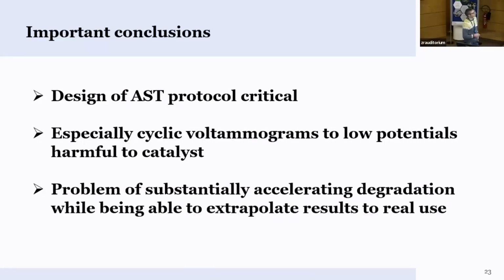So we know that this design is critical, but the design is often a little bit arbitrary, although it's more or less standardized. But it's really important to understand what happens during the different stages of such a protocol. And we know that not only the extension to high potential where you have the oxidation, but also the reduction potentials are quite harmful to your catalyst.